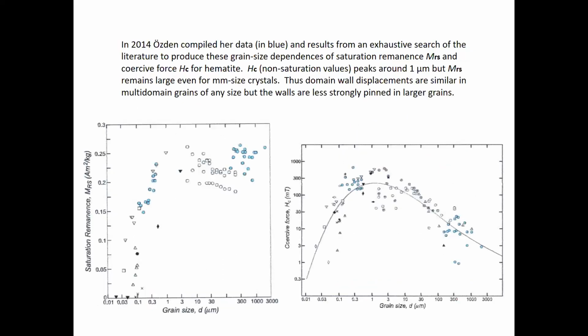And then to finish off, in that same 2014 paper, which is really a massive effort, Özden did an exhaustive search of the literature. And when Özden did a search, it was exhaustive, believe me, she didn't miss much. Showing here that the coercive force has a nice peak with grain size, around 1 micron or so, but the saturation remanence does not. It continues large right up to large grain sizes because of this lack of an internal demagnetizing field. So any little fields you've got left lying around will do it. That will saturate the hematite.